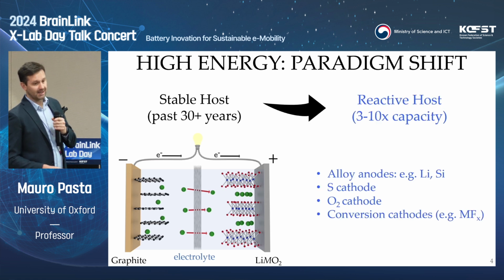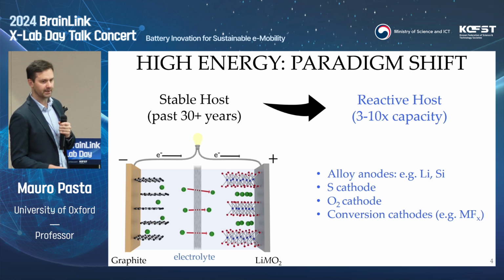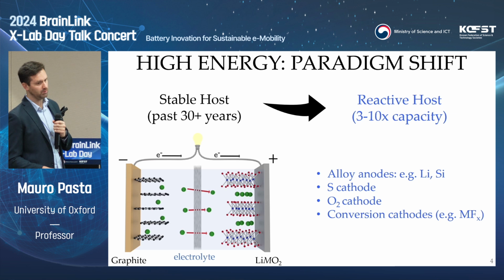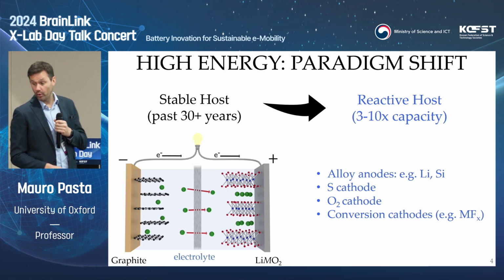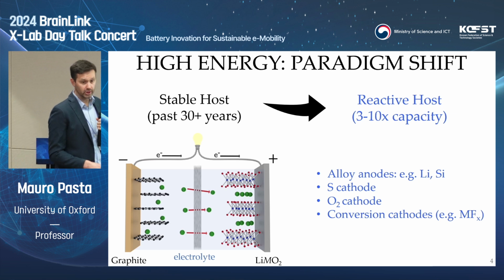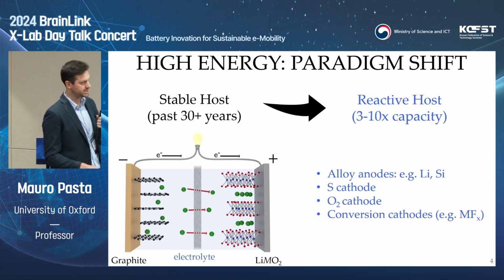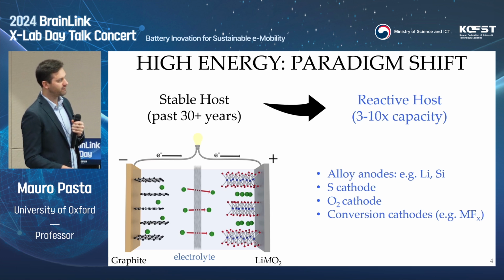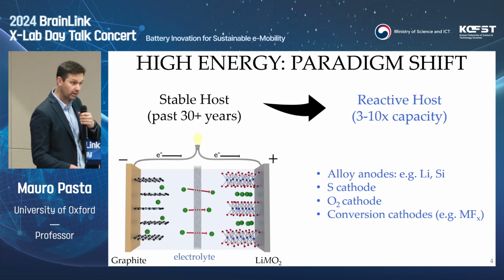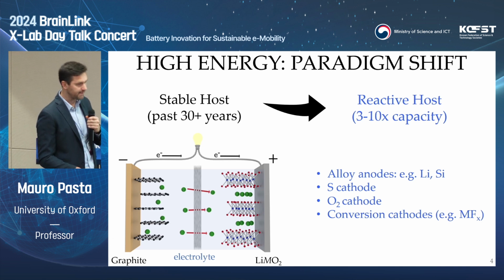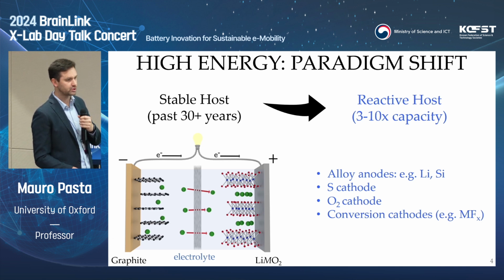If you want to go to the next level, you need to change this concept to what I call reactive host structure. So you can get 3 to 10 times higher capacity by doing so. Examples are alloy anodes. Metallic lithium is the ultimate negative electrode. That will be the focus of my presentation today. Silicon, for example. If you pair lithium with sulfur, you have lithium-sulfur chemistry. If you pair it with oxygen, lithium-air chemistry. You can use conversion cathodes.